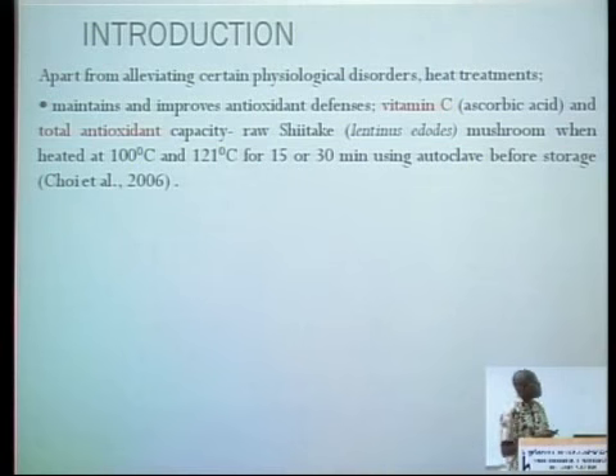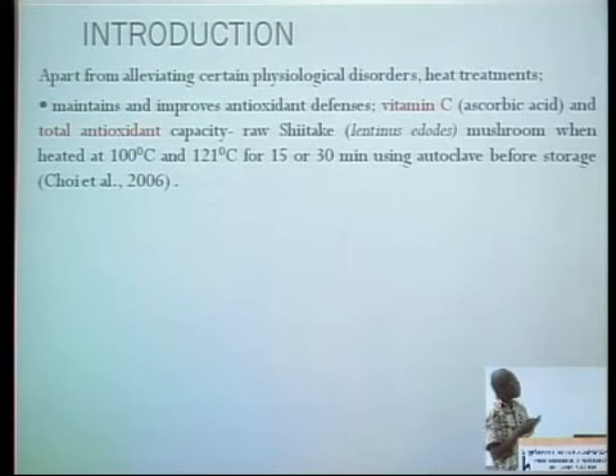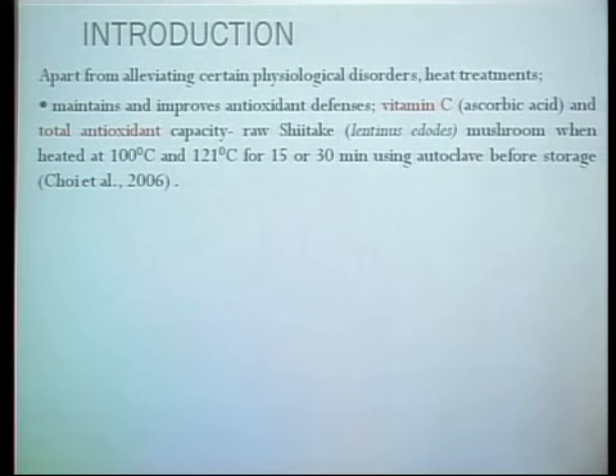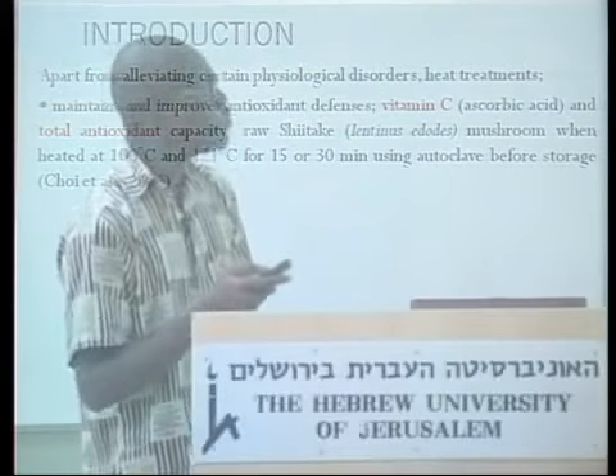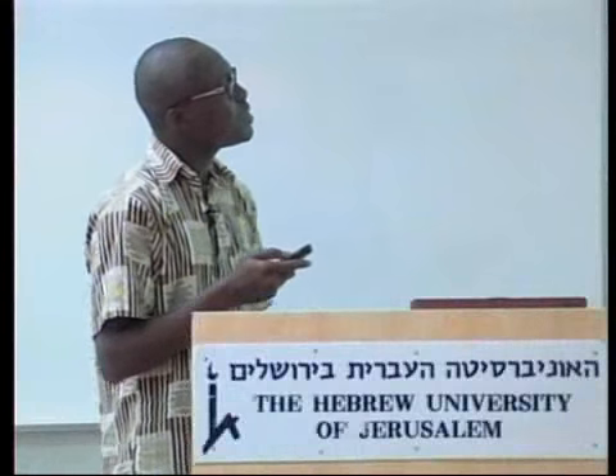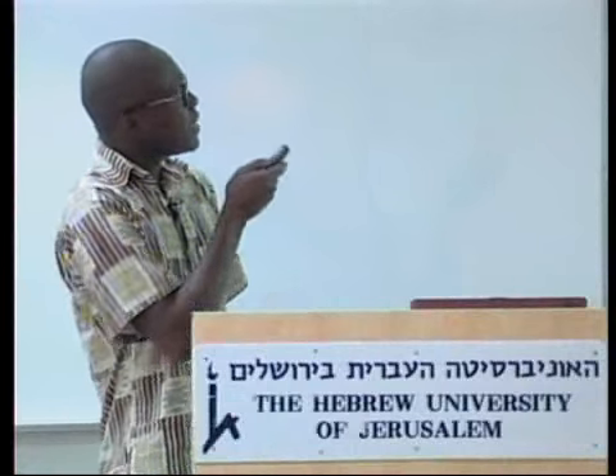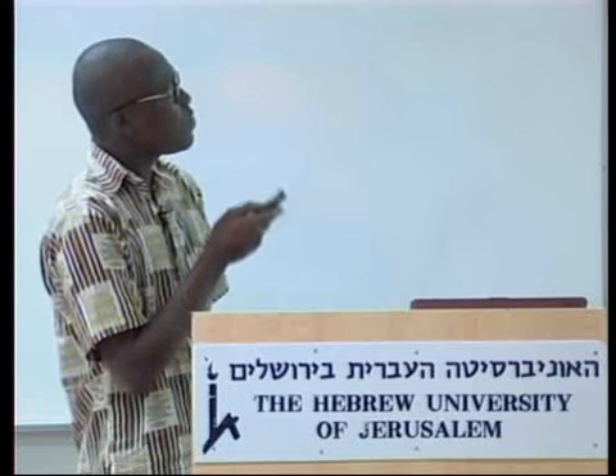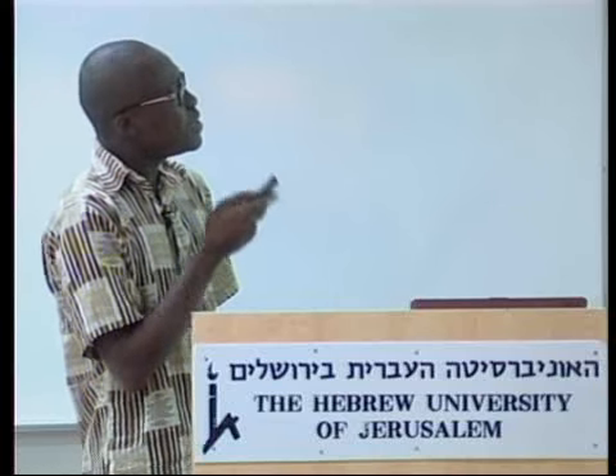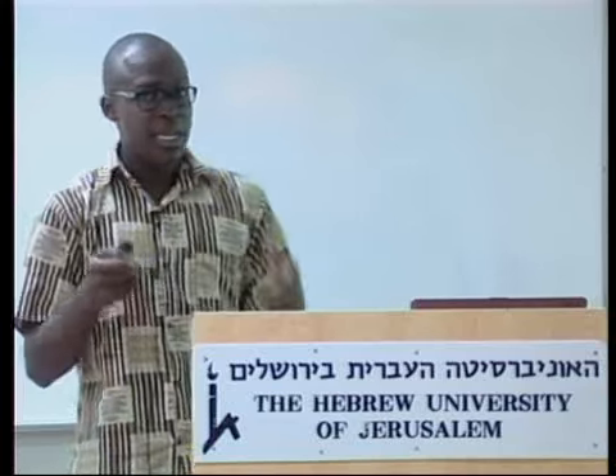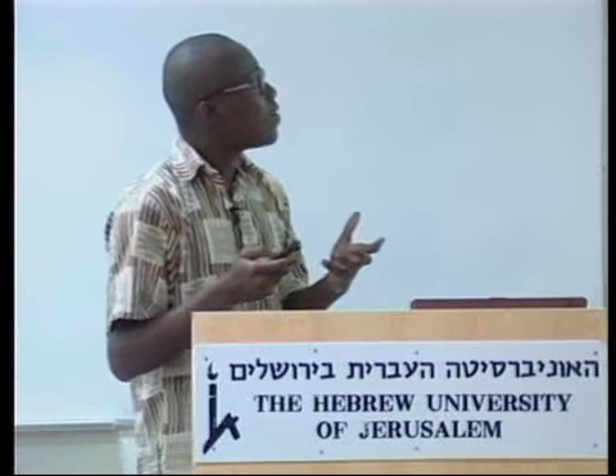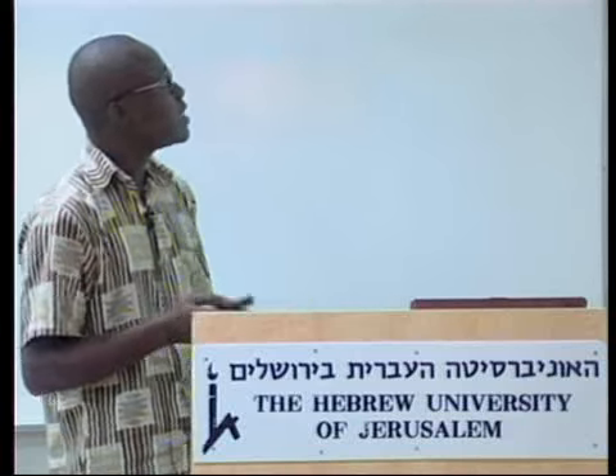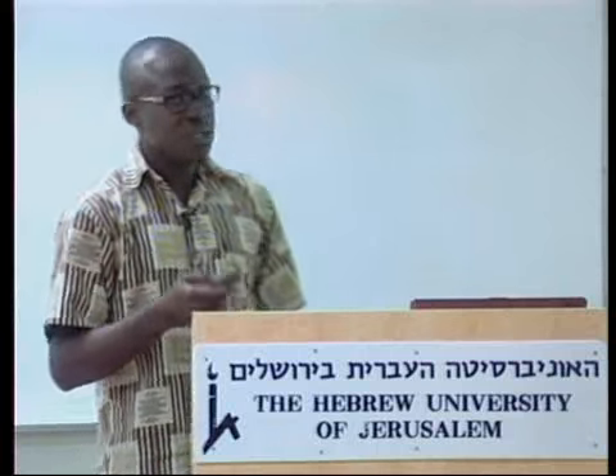But paramount among them is vitamin C. And in an experiment done by Choi et al., 2006, when heat treatment was used for raw shiitake mushroom, Lentinus edodes, at 100 and 121 degrees for 15 and 30 minutes using an autoclave before storage, they observed that the antioxidant activity was maintained